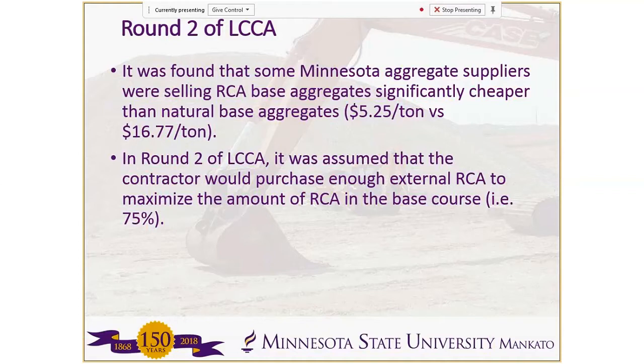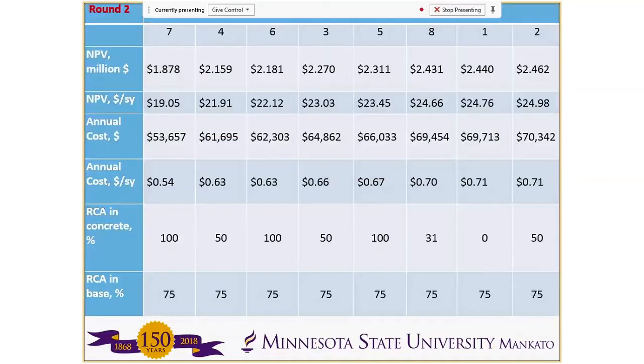And MnDOT allows up to 75% RCA in the base course. So when you do this analysis where you're buying extra RCA to make the RCA content in the base up to 75%, now it favors the use of RCA even more. So now if we look at alternative 7 with 100% RCA compared to conventional concrete, which is number 1, you're seeing almost $5 per square yard savings using the recycled concrete aggregate.